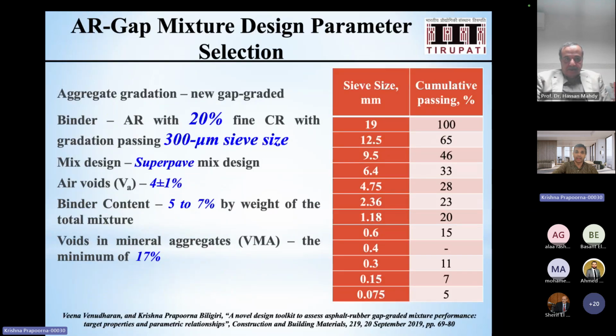So here is the design parameter selection for the entire mixture. So we had 20% rubber passing 300 micron. Okay, and then we use Superpave mix design, unlike the Marshall mix design that is conventionally used. So, and the air voids that you see here, so you can come up with your own design. Okay, when I say this is the design, this is not the end. You can also come up with your own novel design.